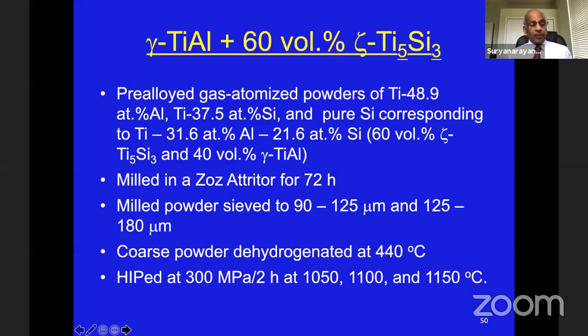The second type of composite I would like to talk about is titanium aluminide containing 60 volume percent titanium silicide. This is a very high volume fraction of a reinforcement in a titanium aluminide. The reason we wanted to check this was titanium aluminide can be superplastically formed around 1300 degrees Celsius. But is it possible that we can reduce that temperature to lower values by having the nanocrystalline or ultra fine grain size?